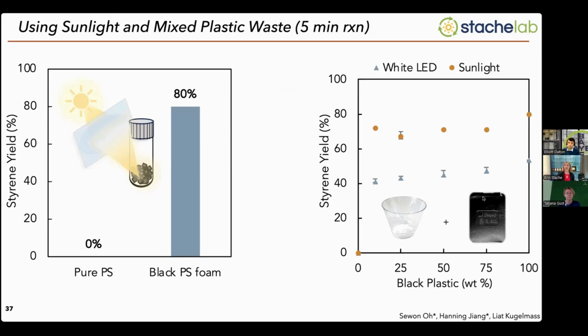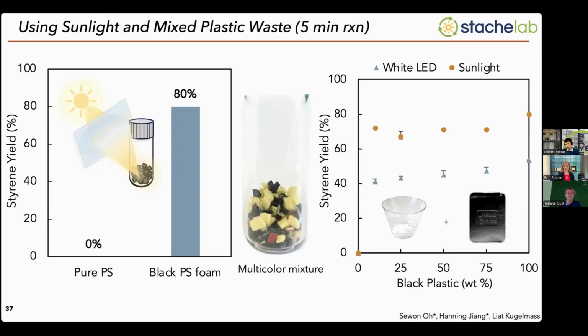So this is using lab LEDs. If we move to sunlight, we can get near comparable efficiencies to our pure carbon black plastic, just using sunlight, and again, using as low as 10 weight% of the black plastic. And to demonstrate this point even further, she found a mixture of other polystyrene products, so yellow styrofoam, a red solo cup, this clear plastic cup, and I think this is 25 weight% of this black styrofoam. Same experiment, mixes it all together. You can see here what the mixture looks like, irradiates it with LEDs. Again, we're seeing about 45–50% yields. And with sunlight, we're seeing, again, near comparable depolymerization efficiencies. So the entire mixture is being depolymerized, not just the black plastic, showing that we can use the black plastic to depolymerize that, as well as other plastics in the mixture.